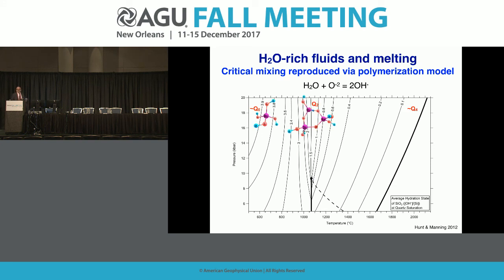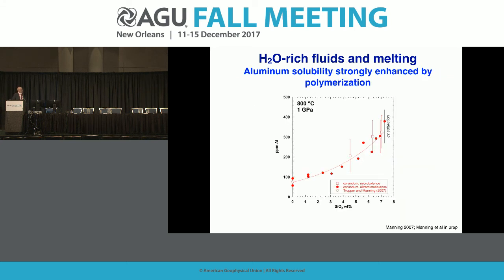The state of aggregation, if you will, the degree of polymerization of the silica in these solutions changes. In the far left, it's mostly monomers. So if you're a person who works on Q species, this would be Q0. There is progressive polymerization. The ratio of OH to silica in the bulk solution goes from a large number, close to 4 here, which would be characteristic of the monomer, all the way down to 0 at dry melting. Again, this is a prediction. This is not fitting any experiments.